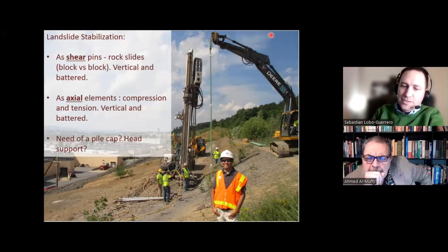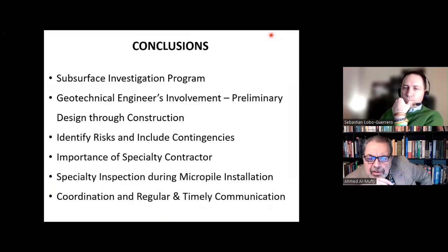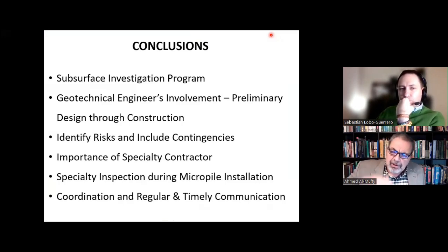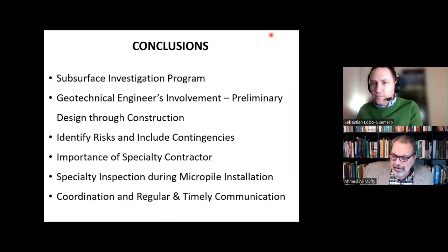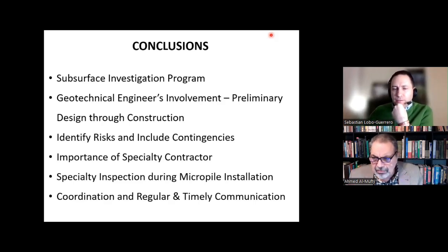So that's typically the way it is. Well, usually if you have a deep environment, the corrosion will not be effective. But because micropiles usually are close to the surface, they are subject to groundwater fluctuation, so they may have a problem with the existence of a lot of oxygen. Correct. I've seen projects where we even add cathodic protection to the micropile reinforcement.